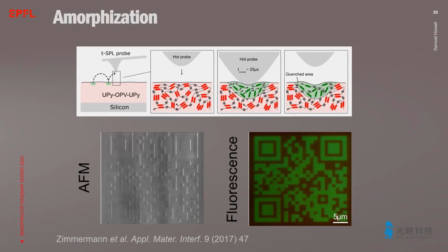So the material is a fluorescent supramolecular polymer, and the monomer can form aggregates which change the fluorescent color in the material. On the macrometer scale, when the material is at room temperature, it fluoresces in red. And when the material is melted above the melting temperature, it starts to fluoresce in green. This is due to the disaggregation of the monomers at high temperatures. This effect is reversible, and at room temperature, when cooled, the fluorescence is always red.